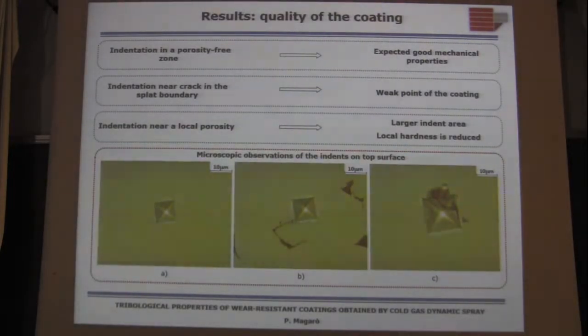In particular, the images of the indents were also analyzed by microscopic observations. The indents carried out on a porosity-free zone could represent a zone in which the mechanical properties are good. But the indentation near the crack in the splat boundaries demonstrates that the crack boundaries can be a weak point of the coating. If the indents were carried out near a local porosity, we can observe a larger indent area and consequently a local hardness very much lower than the other zones of the surface of the coating.